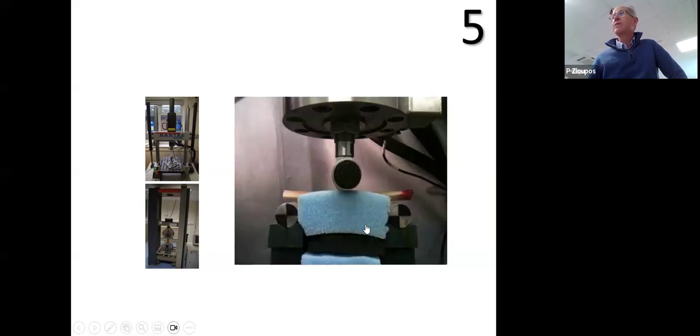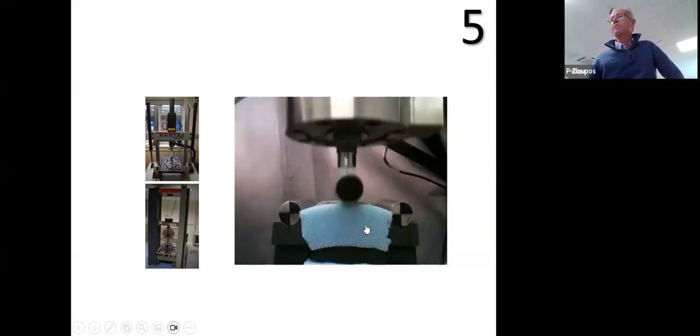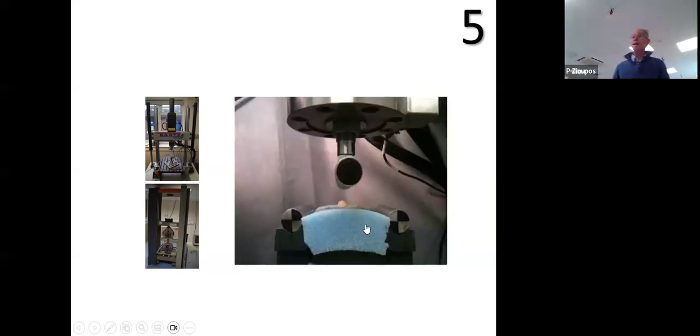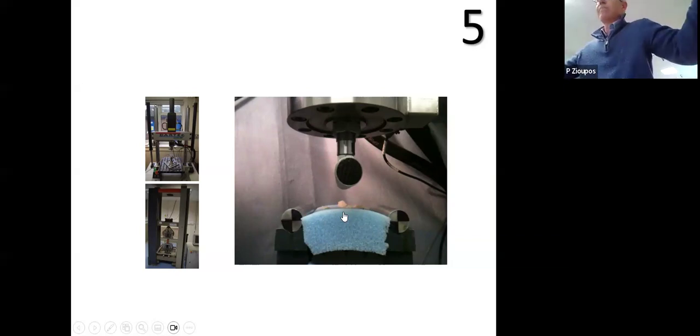So this is breaking half a femur, so it's a semicircle, in a high strain rate, in a quick sort of loading condition. What do you observe? The stored energy is so much that it has fragmented in many pieces, and the two left pieces are just flying away from each other, right? Just catapulted into the room, right?